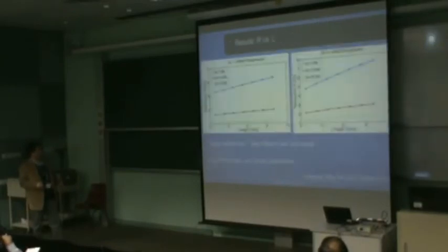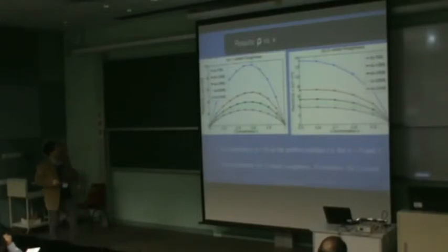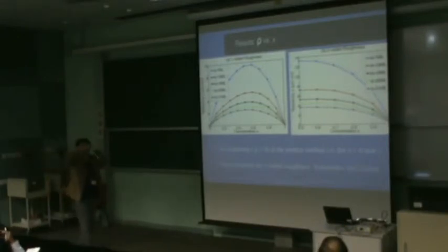So this is a very empirical method, and so our engineering colleagues want to know what is the p, so we can calculate. So what we do is to calculate this using this disorder scattering method, and then you determine resistance as a function of length, and from this slope you get the resistivity, and then you change the thickness of the film, and you get this formula. So basically, resistivity you can determine as a function of the concentration of the surface roughness. What does that mean? How rough it is.